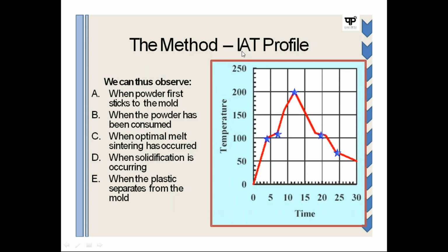Now this is the method, like the IAT profile, you can find it out. A is a point, which is this one. When the powder sticks to the mold, there's a B point, which is this one. When the powder has been consumed, this is the optimum temperature where the sintering, where the fusion is taking place. When the solidification is occurring, it is at this temperature. And E is a point, which is this star, where the plastic material separates from the mold, meaning that once the product is taken out.